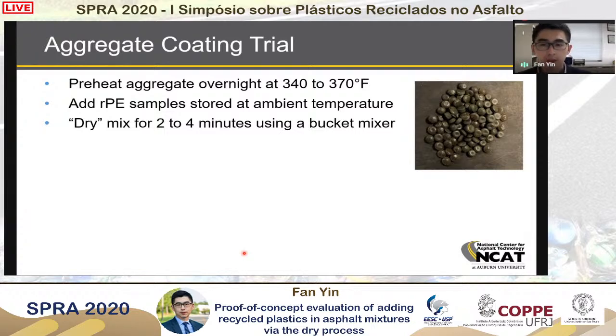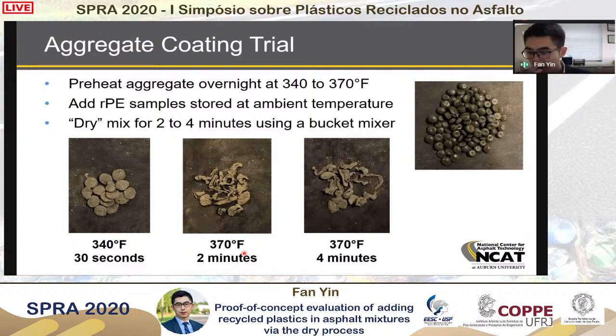And then we're going to do a dry mixing without adding binder into it. And depending on different times, we look at what kind of interaction happened between the plastics and the aggregates. So very interestingly, this is what we found. After we mixed the aggregate with the plastic, we can separate the plastic particles from the batch. So right now I'm showing 3 pictures. The one on the left is a relatively lower temperature, 340, and dry mixing 30 seconds. The one in the middle is a 370 degree Fahrenheit for the aggregate temperature, but we were mixing for 2 minutes. And finally, on the right side is the same temperature, but we extend the mixing time to 4 minutes.